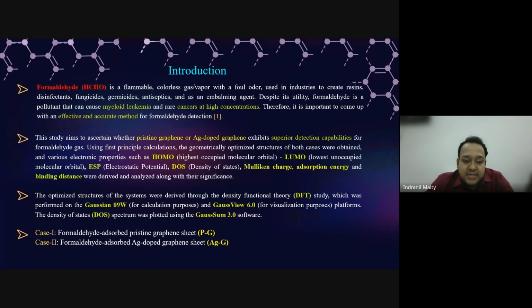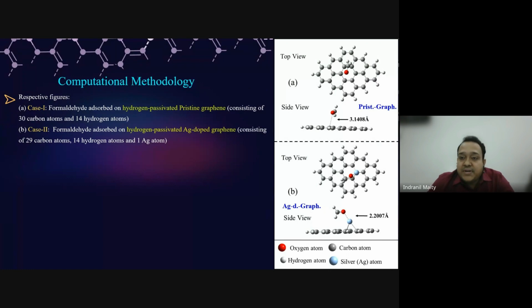And case 1 denotes formaldehyde adsorbed pristine graphene sheet, short form PG, and the second one is case 2, formaldehyde adsorbed silver doped graphene sheet. The short form is AG-G, that is silver doped graphene. So two different structures have been considered. On the right side, the first figure represents the pristine graphene sheet, and the bottom one represents the silver doped graphene sheet. Here, a carbon vacancy was considered in the second case, over which the foreign atom silver was placed.